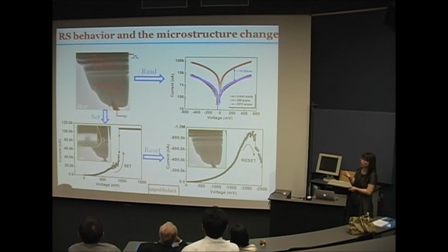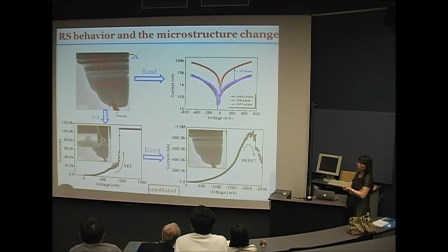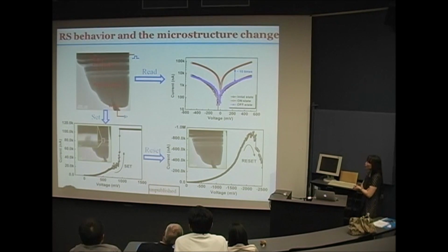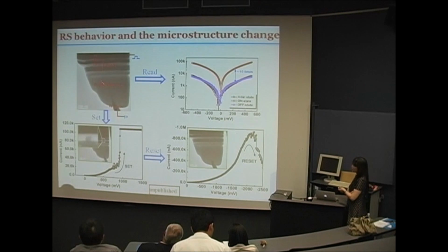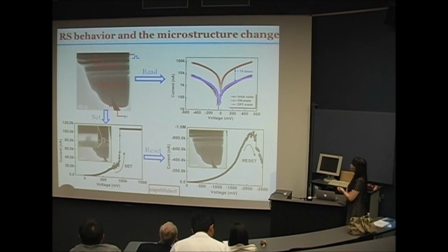This is a very challenging job, because doing a TEM experiment on a device like this, it is very difficult to make the samples. This sample device has to be fabricated on a tungsten tip, so it is not easy to succeed in the sample preparation. But actually, after 1.5 years and a lot of experiments, we finally succeeded. This is the total device fabricated on the tungsten tip, so we can do in-situ TEM observation.